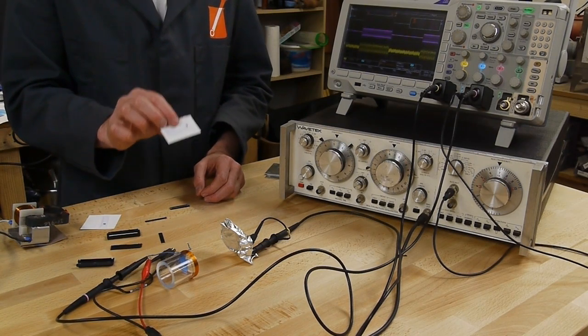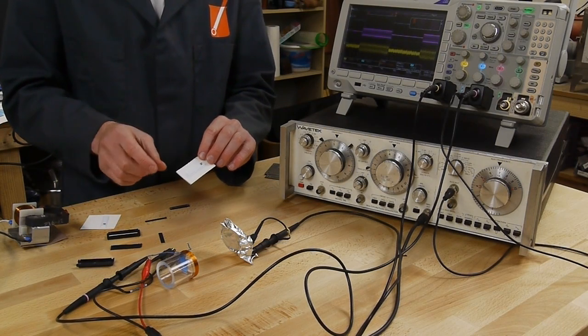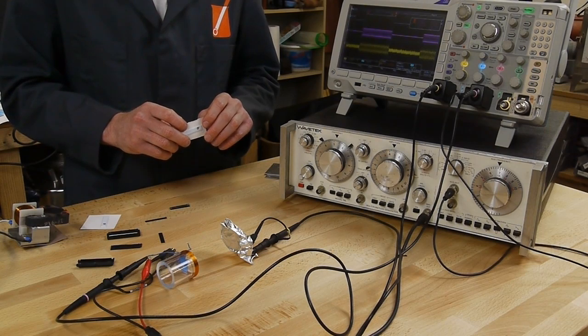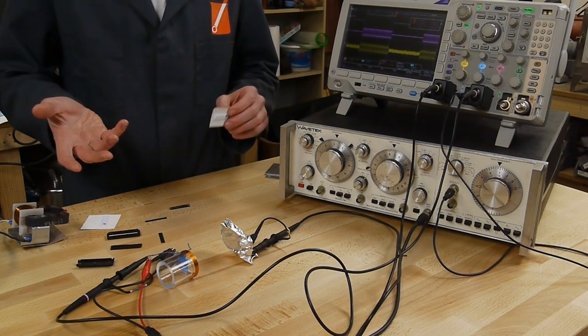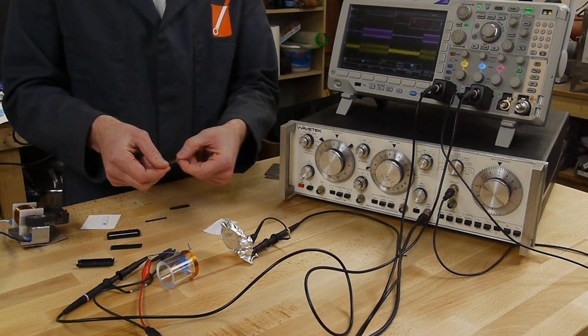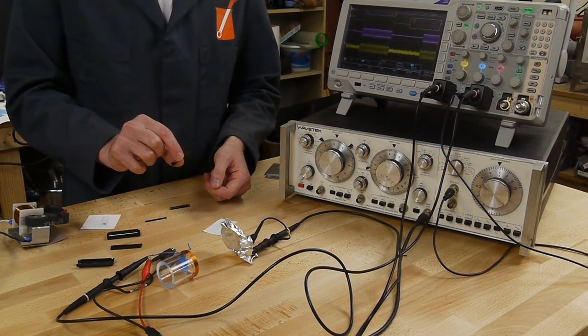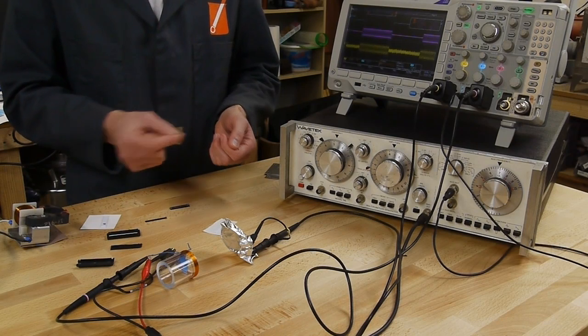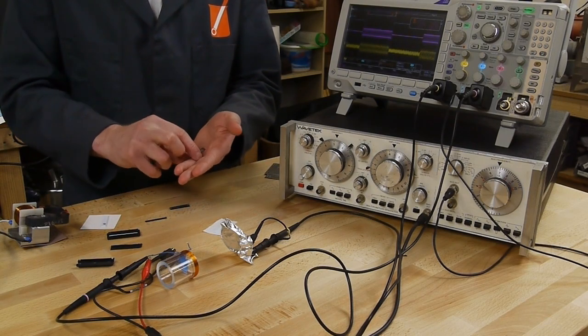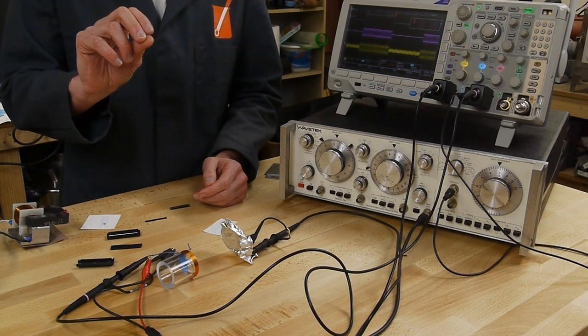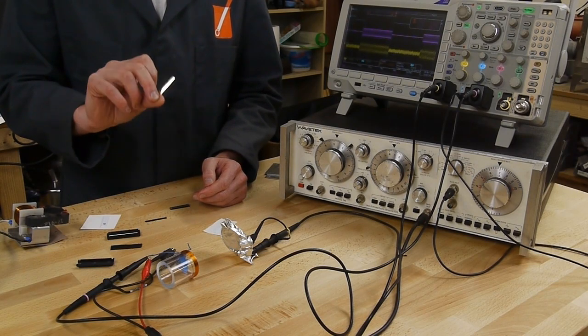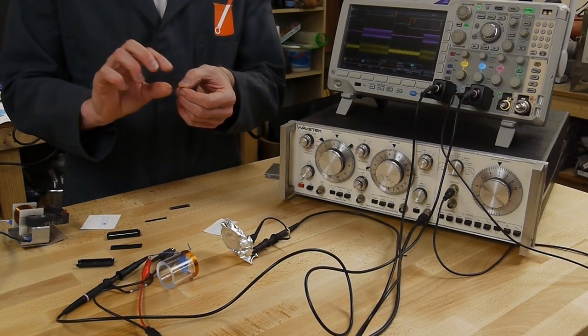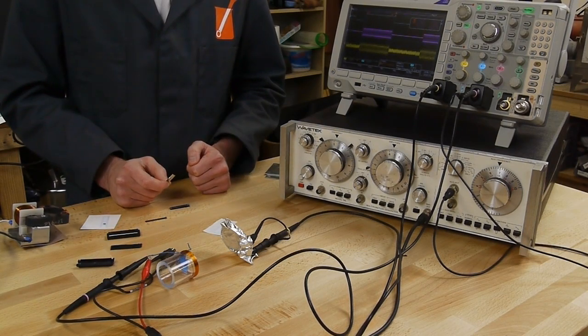There's no sound being transferred from this back to the system. The only acoustic part of it is the fact that it's using this ribbon that mechanically oscillates at about 58 kilohertz. It's easier and cheaper basically to do it this way than to build, for example, an inductor capacitor network that would oscillate at a similar frequency. This is just a piece of metal, it costs very little. This is about 25 micron thick. It actually is a special alloy, but it's not that exotic - it's mostly iron. Making these tags is super cheap.